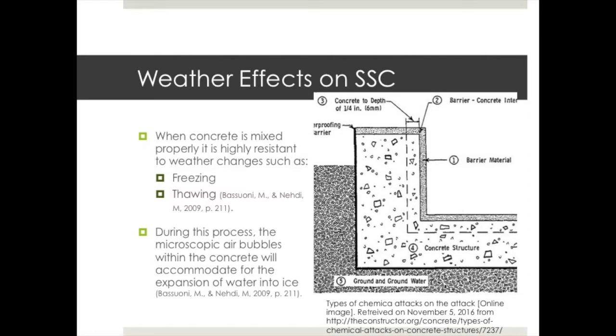When self-consolidating concrete is mixed properly, it is highly resistant to weather changes such as freezing and thawing. Self-consolidating concrete can resist freezing and thawing because of the microscopic air bubbles within the concrete that will accommodate for the expansion of water as it turns into ice.